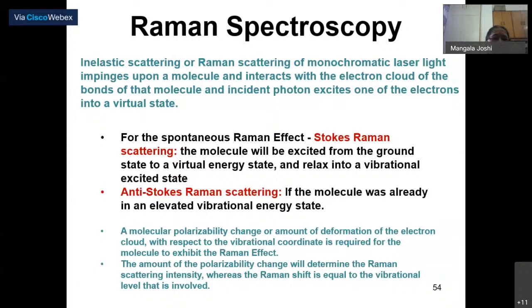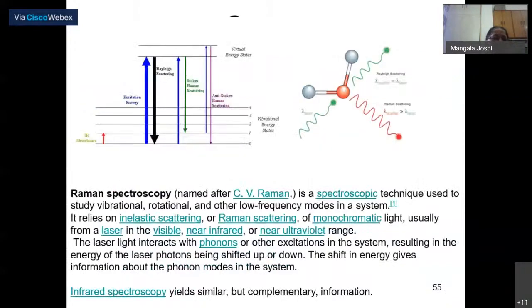Inelastic scattering, or Raman scattering: monochromatic laser light impinges upon a molecule and interacts with the electron cloud of the bonds of that molecule, and the incident photon excites one of the electrons into a virtual state. For the spontaneous Raman effect, Stokes Raman scattering, the molecule is excited from the ground state to a virtual energy state and relaxes into a vibrational state. On the other hand, if a molecule is already in an elevated vibrational state, it is called anti-Stokes Raman scattering. For Raman scattering, molecular polarizability is very important, and the amount of polarizability change will determine the Raman scattering. That is important to get information about the changes you have made in the sample. So you are basically looking at Stokes Raman and anti-Stokes Raman scattering, and because of a change in the sample, there will be a shift in the Stokes and anti-Stokes Raman frequencies. That gives you information about the change in the sample chemistry.